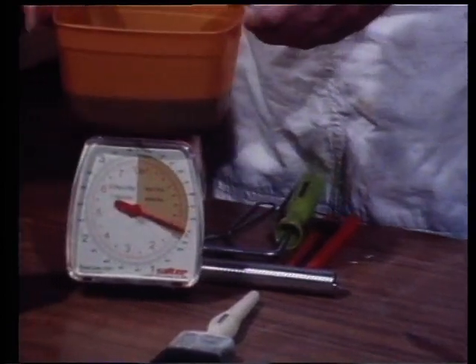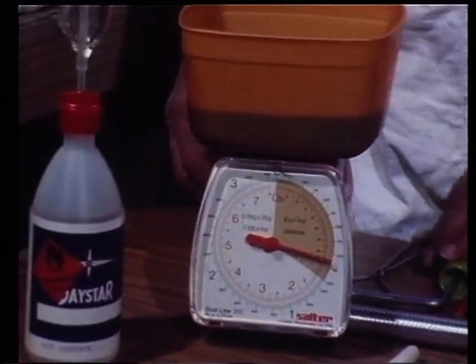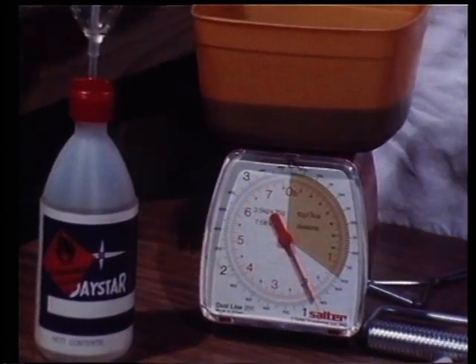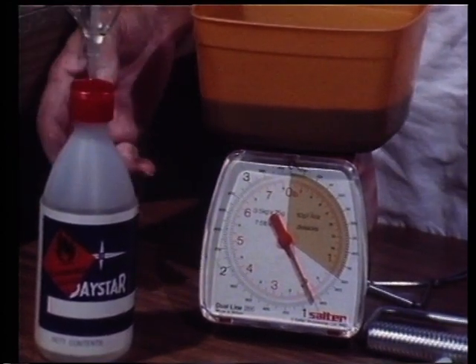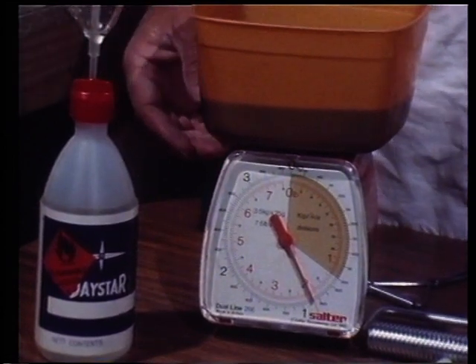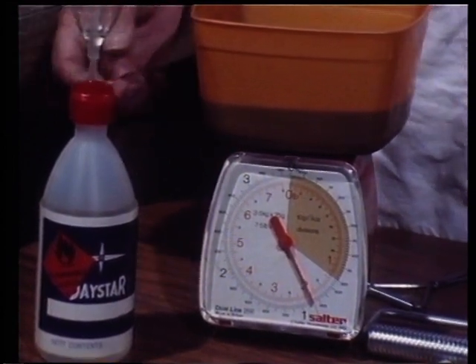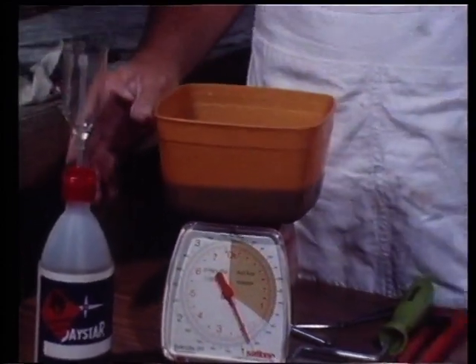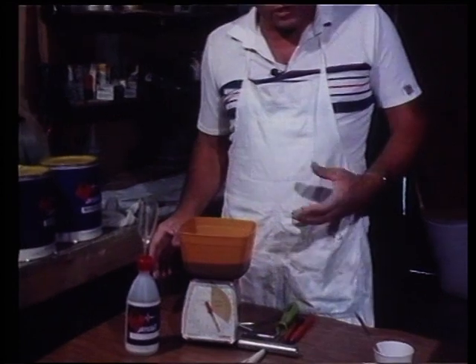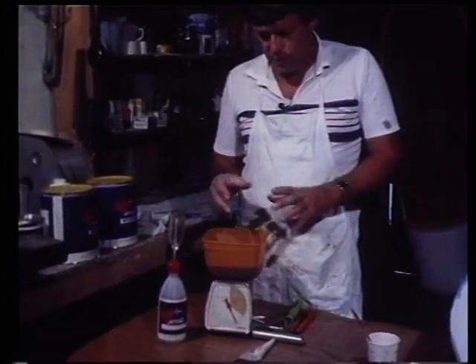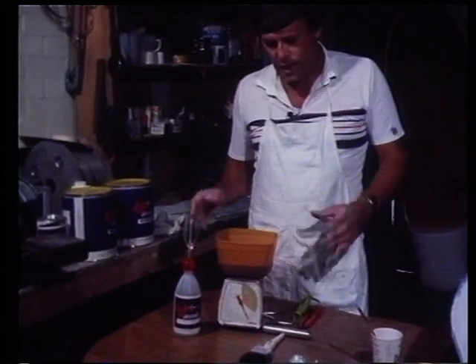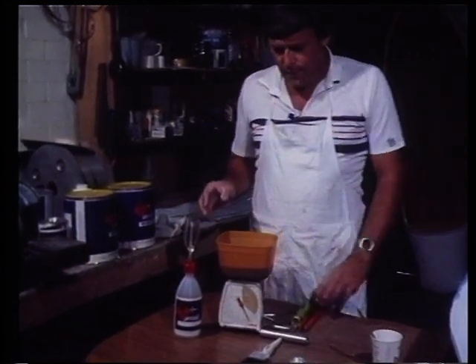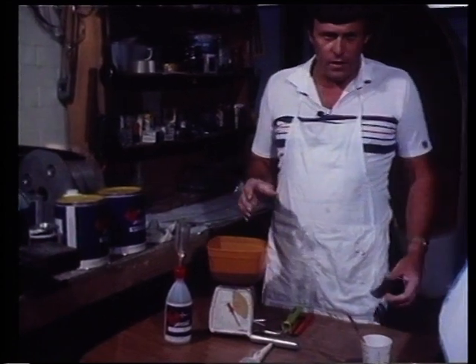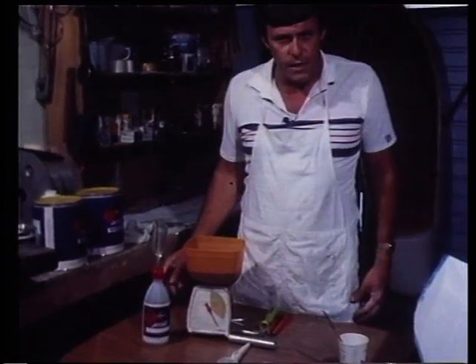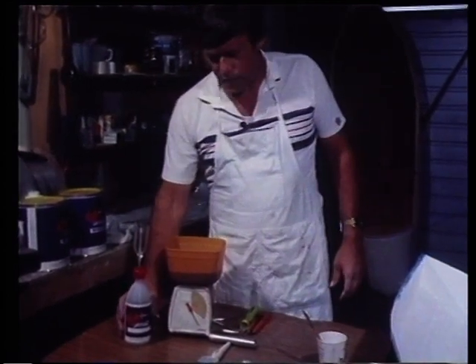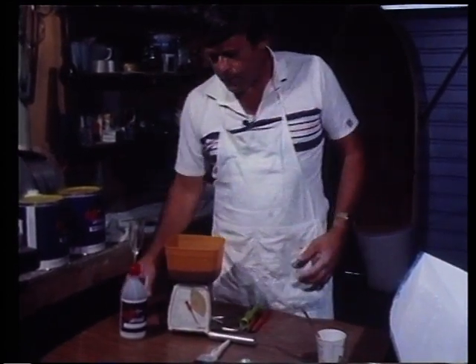So the amount of catalyst that you can use varies widely according to the conditions. If you have any catalyst in there at all, down to a very, very low percentage, the reaction will be started and the cure will be affected. Now, if you have only a very small amount of catalyst, that will take a long time. If you have a large amount of catalyst, it will take a very short time, and in the process generate so much heat that it's possible for this to fume and crack and melt the pot that it's sitting in. So somewhere in between we have to strike a compromise. And the amount of catalyst that we use is governed by the conditions on a given day. But for normal room temperature, which is pretty well universal, we use 1%, which is 10 mils to the kilo.